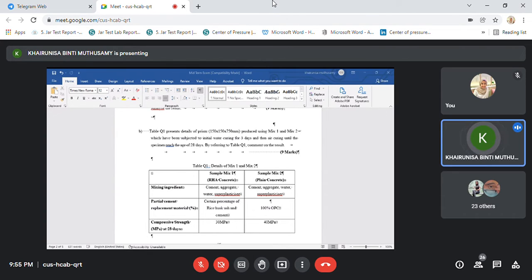Okay, when we use excessive use of RHA or too little, it will affect the strength of the concrete, due to the pozzolanic reaction issue. Let's say you can assume the use of RHA is too high, so it affects the pozzolanic reaction. As the cement content is greatly reduced, that will reduce the quantity of calcium hydroxide generated, which is also important for the pozzolanic reaction to take place.